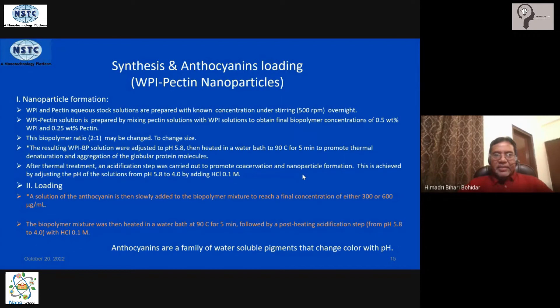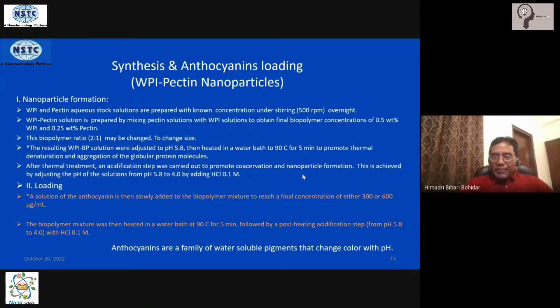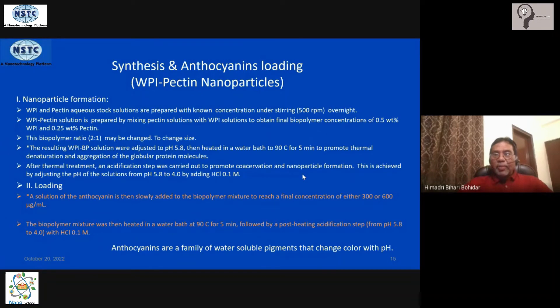After mixing, the pH will settle around 6. Heat the mixture to about 90°C for approximately 5 minutes. During heating, the protein undergoes denaturation. After denaturation, the protein starts forming aggregates of globular protein complexes — these aggregate structures then serve as the substrate to which pectin will bind.